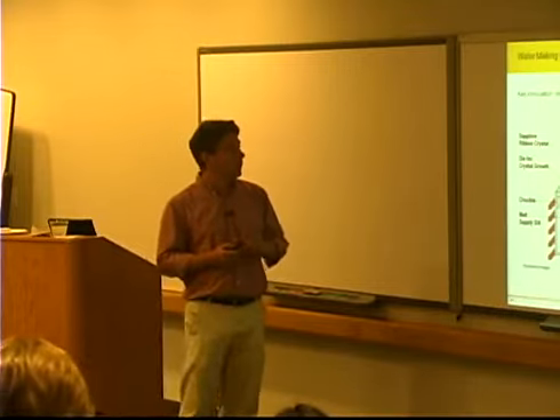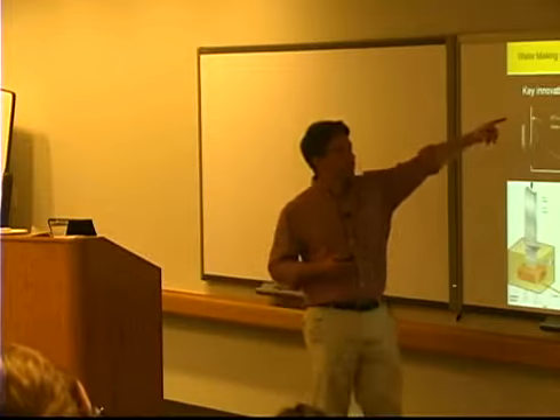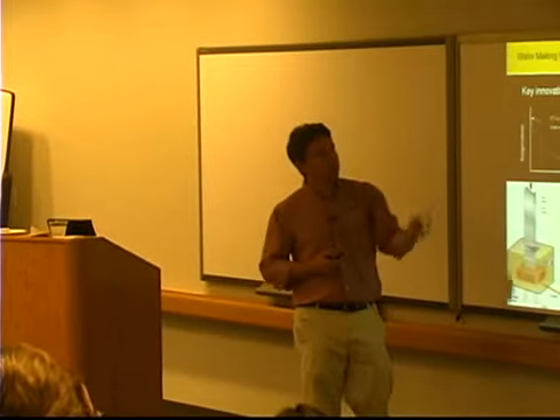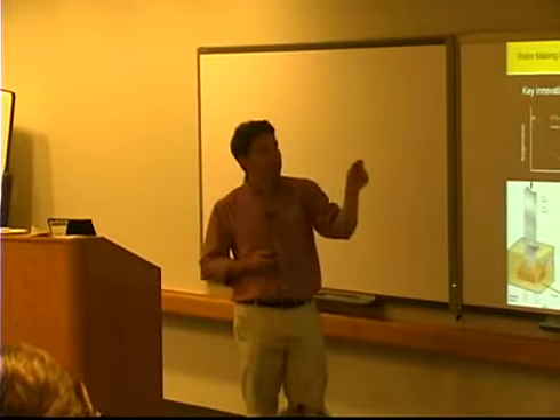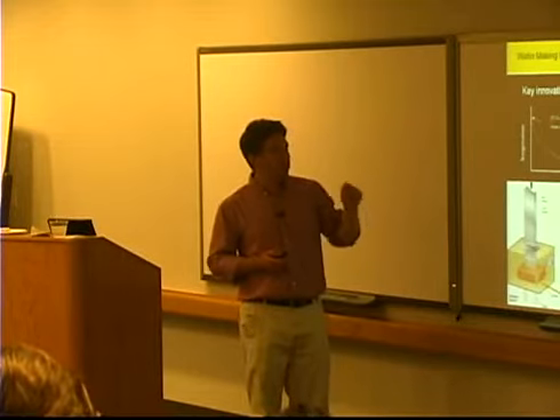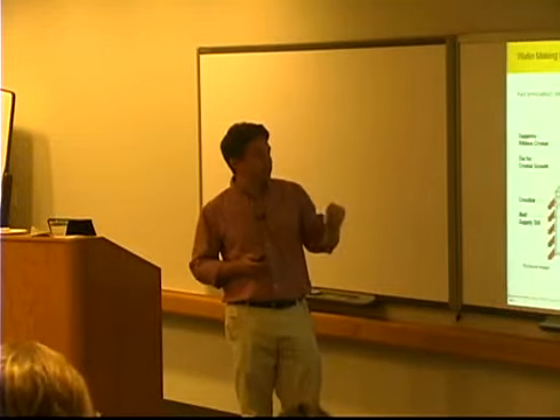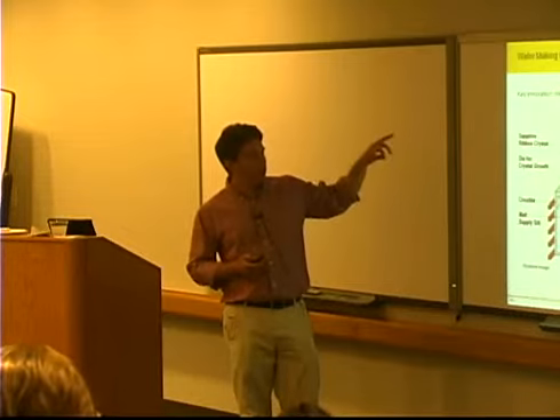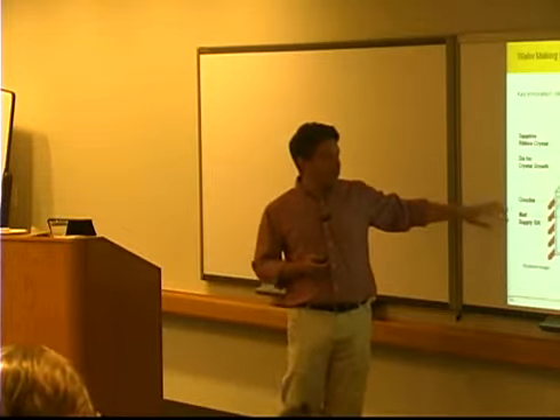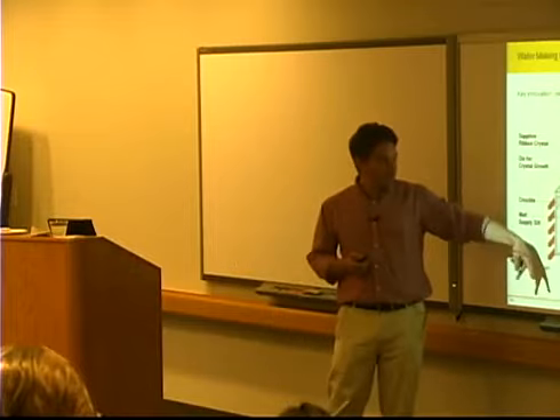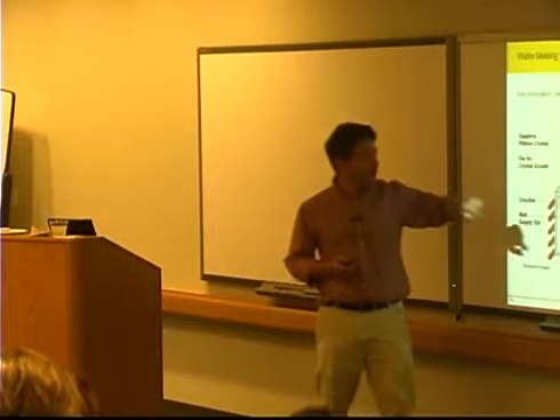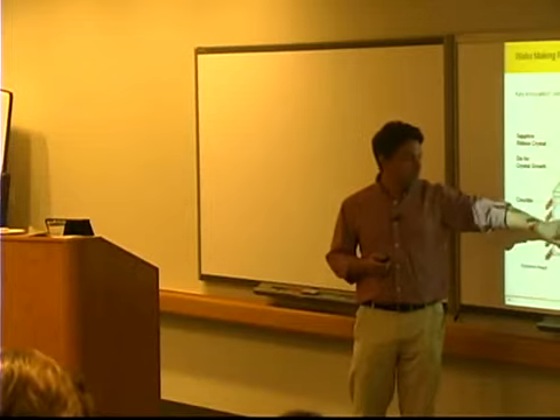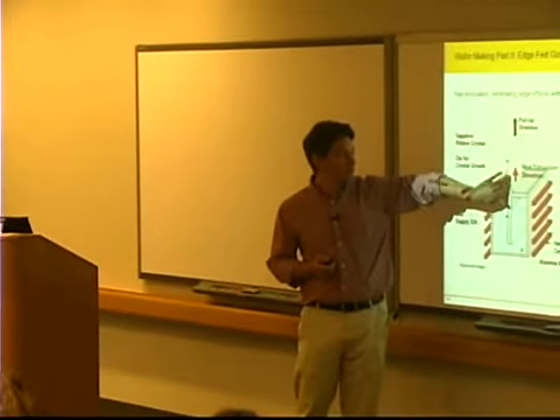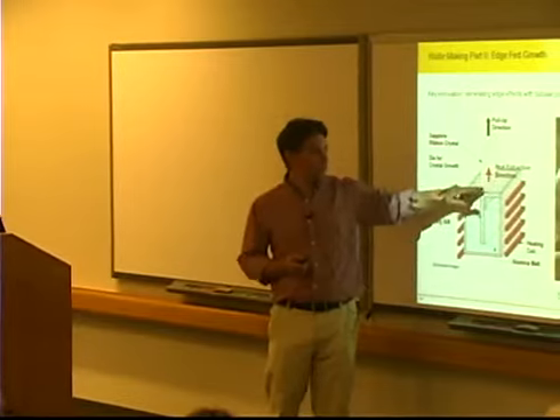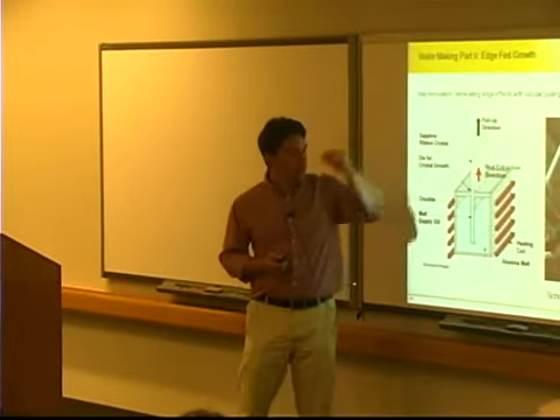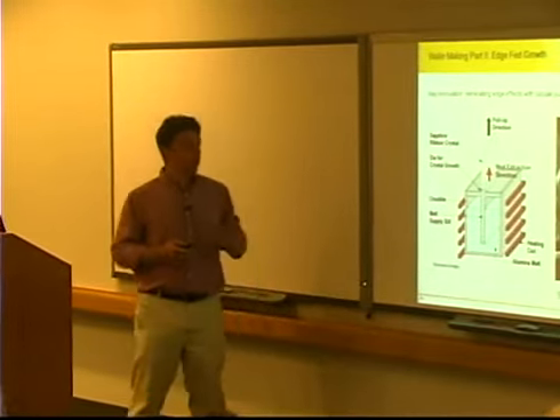So the main innovation here, though, is managing this surface tension and being able to pull this very thin wafer between these two filaments. And it's really a nice process. Another process came about around the same time that instead of pulling up a meniscus with filaments, more or less used a pressure situation to push liquid up through a die and then to pull the wafer up, no strings attached.